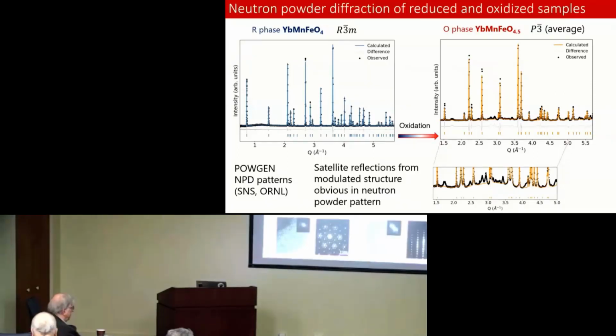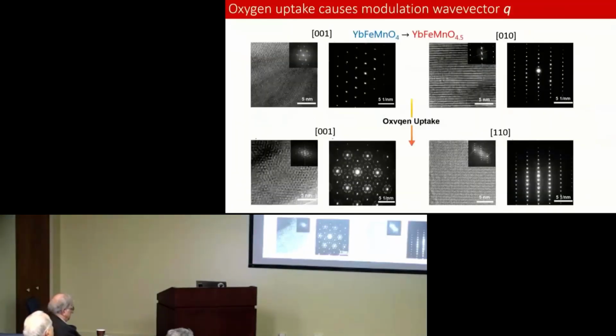And so my student Tianyu was able to do some really nice electron diffraction, looking down, say, the 001 zone axis. Here's the reduced phase. And then upon taking up oxygen, you see all these nice little satellite reflections that pop up to make this image here. If you look down different zone axes, as you go from rhombohedral to the trigonal, you change bases, but nevertheless, you still see some nice superlattice reflections here.